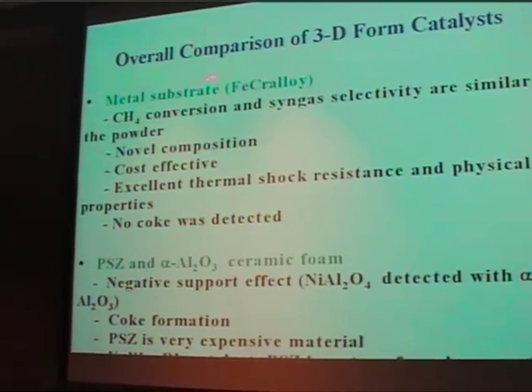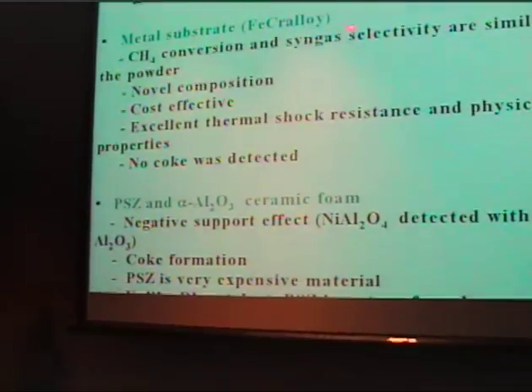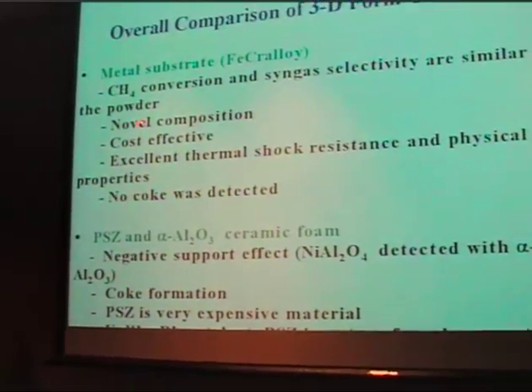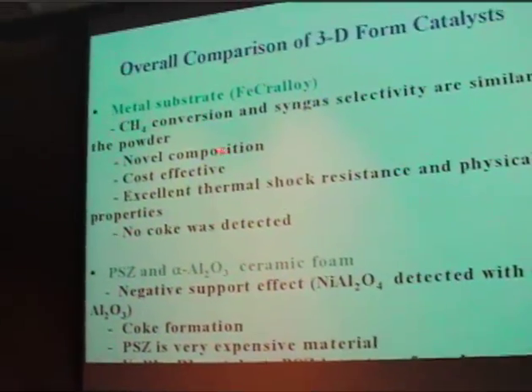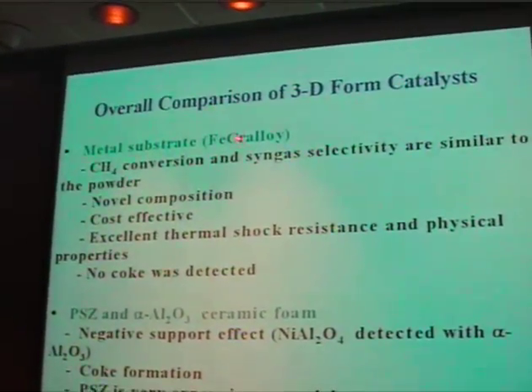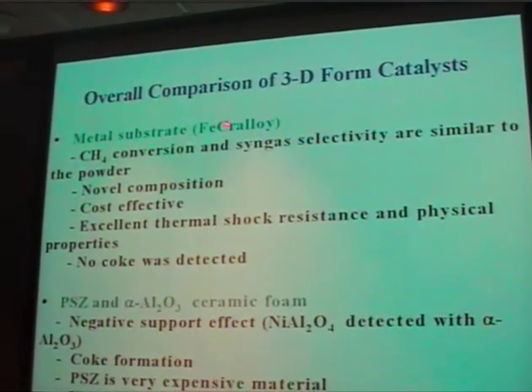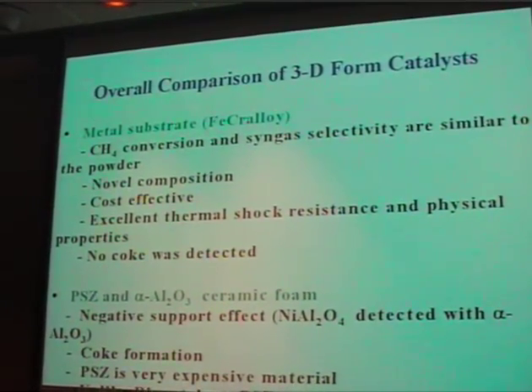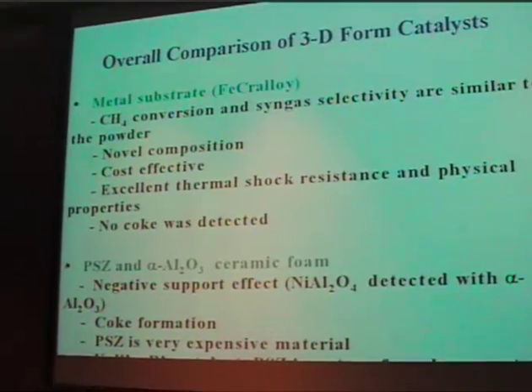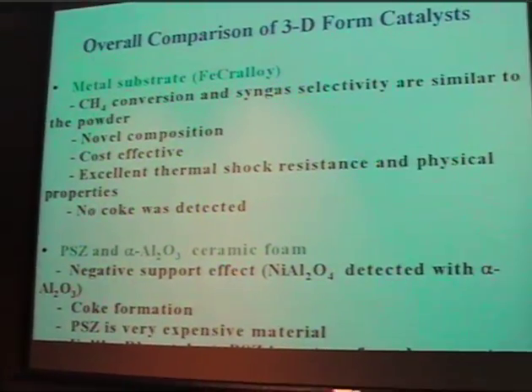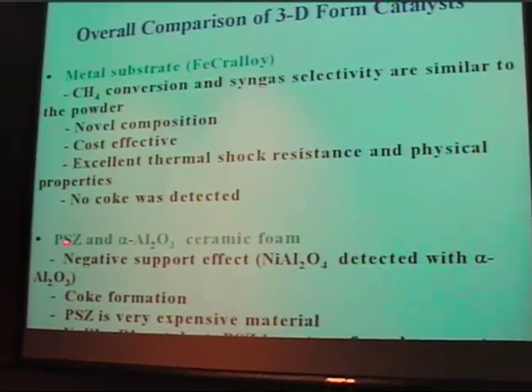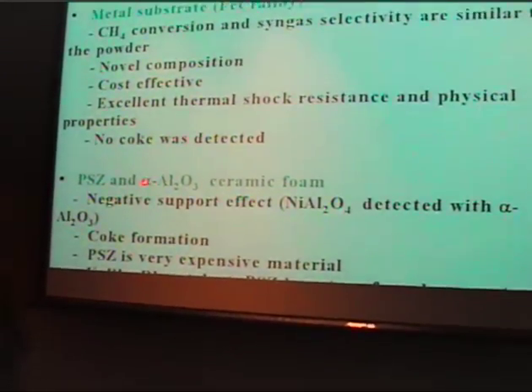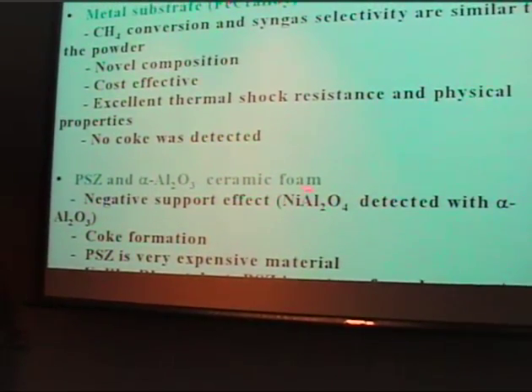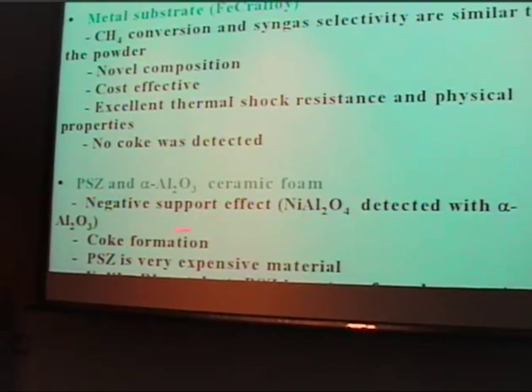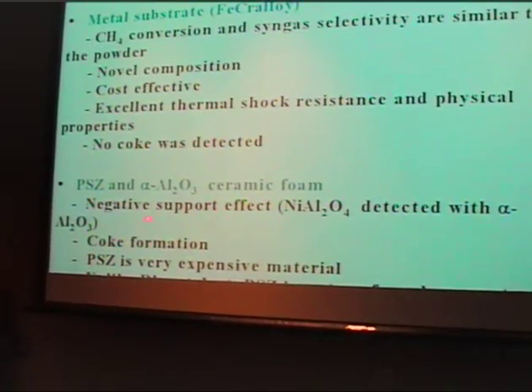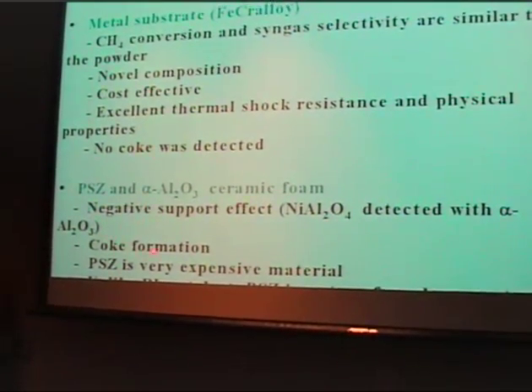more on the 3D structures. Here we have the FeCralloy. This is a very novel composition. You don't see this too often in the patent literature, using this as a support, cost effective. That one panned out well. We weren't too high on the partially stabilized zirconia or the alpha alumina because we did see some nickel aluminate forming, which would be bad. That would cause the catalyst to deactivate and coke.